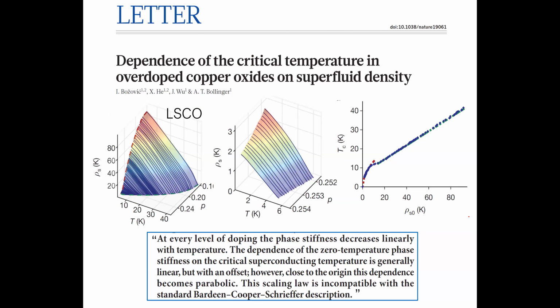On the other hand, there's been a bit of controversy regarding this question, raised to a large extent by Ivan Bozovic, who made a series of very finely spaced in oxygen concentration LSCO films, epitaxially grown at Brookhaven. And you see here a plot of the superfluid density that he measured in Kelvin units versus doping and versus temperature. And there are several things to note here. This is on the left, the full data set, and then on the right, the high doping and low T_c data set blown up.